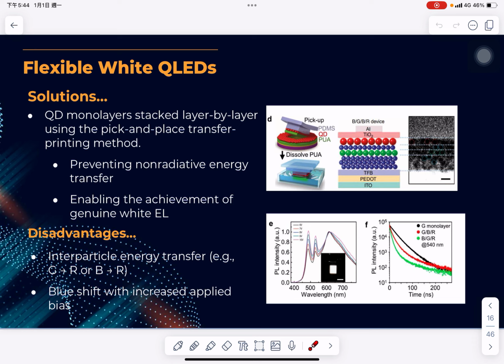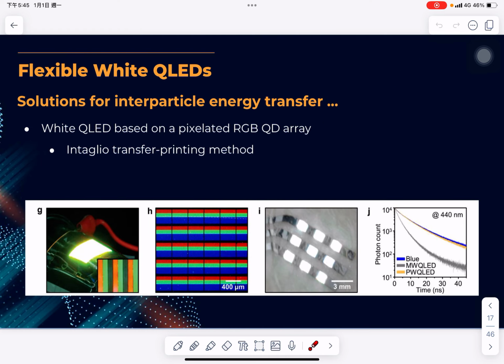Vertical quantum dot layering induces energy transfer, like green to red or blue to red, due to stacked quantum dots in the charge injection direction. Increased bias causes a blue shift in the EL spectrum by boosting larger bandgap quantum dot contributions. The use of pixelated RGB quantum dot arrays in white QLEDs, like this kind, solves energy transfer issues.